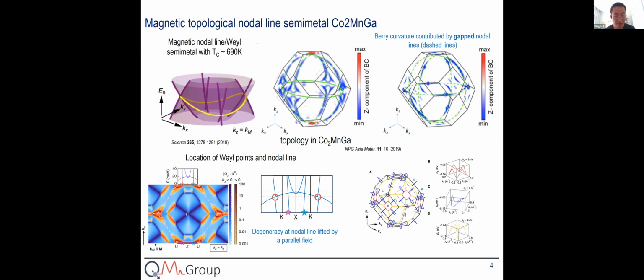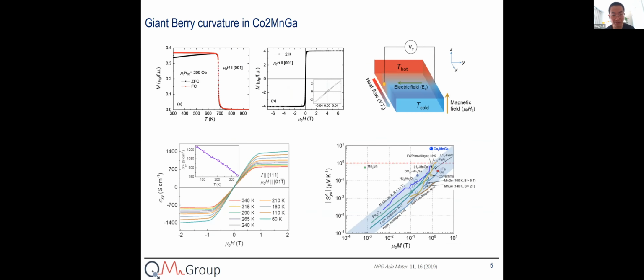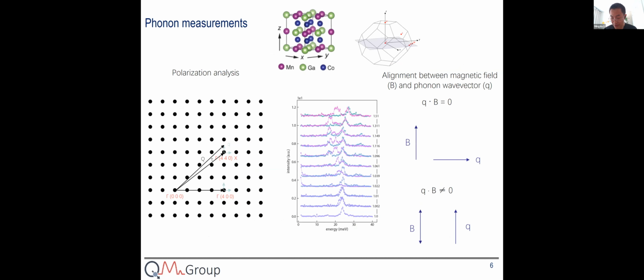That's why in the past few years, people have confirmed this material has all kinds of different types of nodal lines and even Weyl nodes, and together with the magnetism, the interplay becomes an interesting question to answer. Besides some fundamental reasons, this material is also interesting from an energy harvesting perspective. One is that it has a very large Nernst effect. People have been measuring this: if you have a longitudinal heat current, like in the X direction, what is the voltage response, coming solely from the intrinsic Berry curvature of the topological nodes. This material is probably one of the largest, even larger than iron and platinum multilayer materials. In addition to that, we want to study why those topological features can have any signature on phonons.